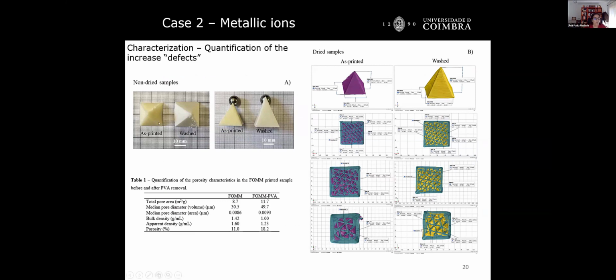So first of all, for the non-drying sample as printed after washing, what you see is an increment of the shapes, of the sizes of the pyramid, because the pyramid was the best one with that pink yellow color. And then when you dry, even the washed one, you have some difference in size, okay? But what you have is not very different. Then we took these pyramids, so these are the CT scans, and tried to quantify the increase, and it showed an increase in the porosity.